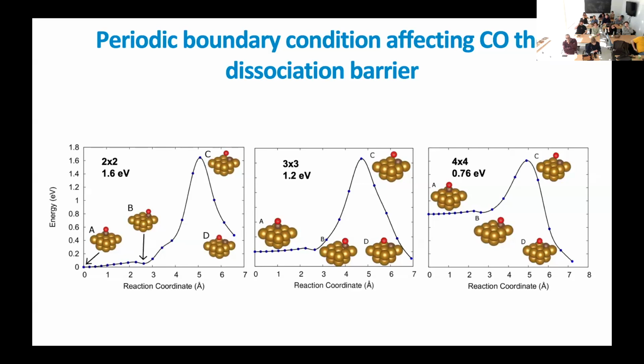And what made us believe that there was something wrong is that the barrier that we were finding was really too high to explain any decomposition happening at 550 Celsius, right? So this is why we had to increase the size, and hence we ended up with this barrier. What is interesting is that, as the previous talk was also explaining, you start from a situation where CO is tilting and bending. After that, it decomposes, okay, and it goes to a minimum which is much more stable than the initial minimum, which explains why you will have these stable carbide formations at the end.